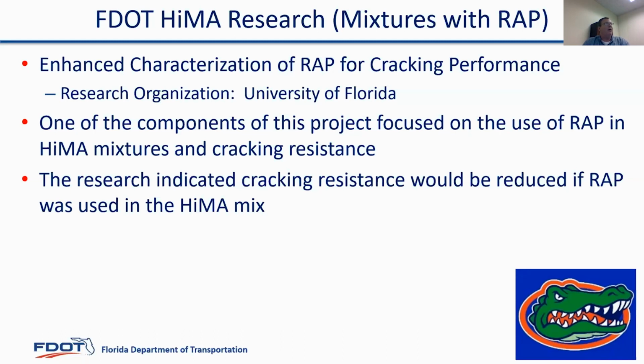So again, the primary focus was RAP usage in general, but one of the aspects of this research project was to look at the effect of putting RAP in a Florida HiMA mix with respect to cracking resistance. And the research showed you would see reduced cracking resistance in our mixes if you put the RAP in with the HiMA binder. So that's why we continue not to do that at this time. With some of the more recent work with binder availability when RAP's used, maybe if you put more binder in, you might get a better result. But that's just what we found with our mixes.